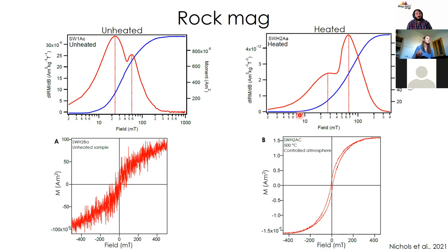So I did some rock magnetic studies on the samples before and after heating. Before, this is IRM acquisition, so we have a population of fairly low coercivity grains and then a smaller peak of slightly higher coercivity grains. Whereas after heating, the peaks completely change and you have much higher coercivity carriers post-heating. And with the hysteresis behavior, it's very unstable prior to heating, and after heating we're getting nice single domain carrier signals. So that was a bit suspicious for us about what we were doing.